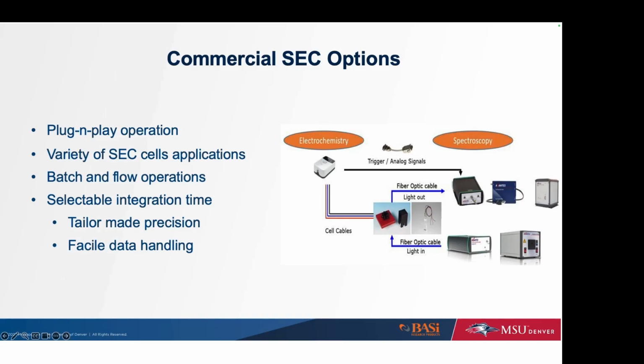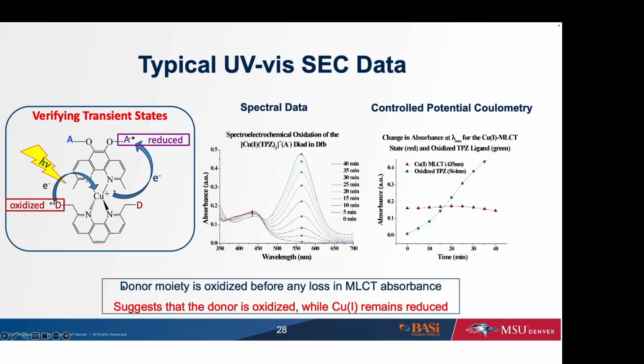And so, to follow up or to wrap us up with the final, what would you see from the data in a transmission UV-Vis spectroelectrochemistry setup? This is one example, and it's from my graduate work, but I had it, so I figured I'd use it. You end up getting two pieces of data, especially if you do this as a controlled potential electrochemical measurement. You can also do a cyclic voltammetry type of measurement, but in this case, we did a controlled potential coulometry, and we stepped the potential to about 100 millivolts past our E1/2 to oxidize our donor.